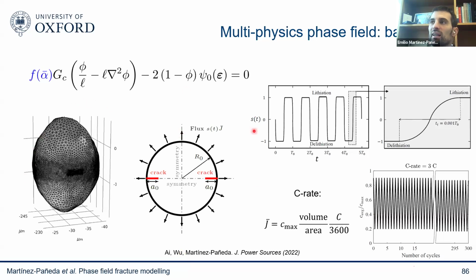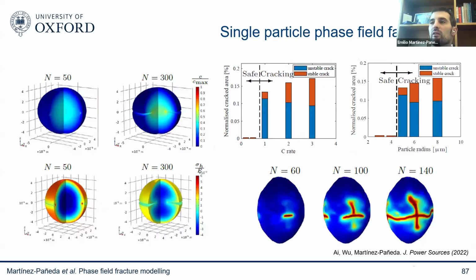And basically we look not only at idealized particles, but also realistic particles that we took from XCT scans. And then we could simulate hundreds of loading cycles, which is relevant for electric vehicles, for example, or phones. And they were able to predict, as a function of the C-rate, as a function of the charge and discharge cycles, what is the propagation of those cracks. And you see some examples here of those cracks growing in idealized particles and realistic particles. And you can see that we can vary anything we want.